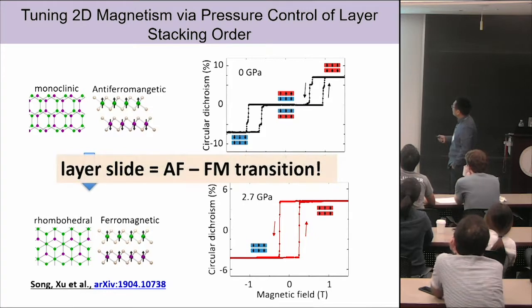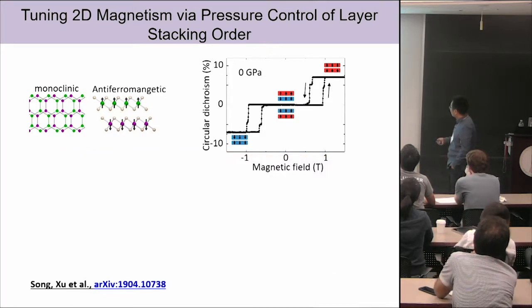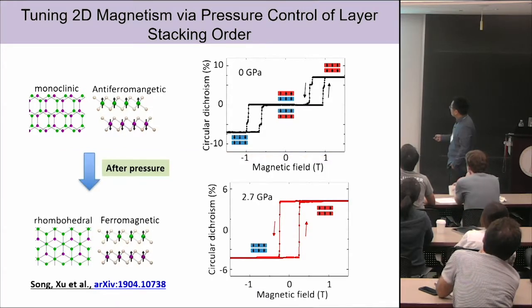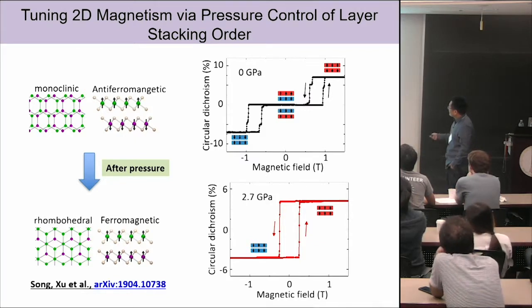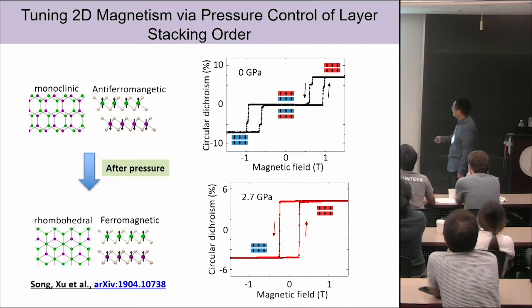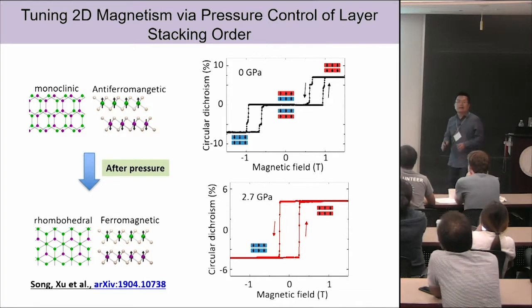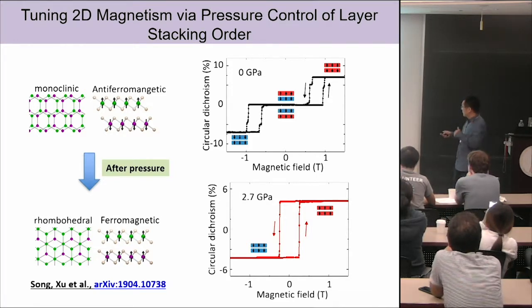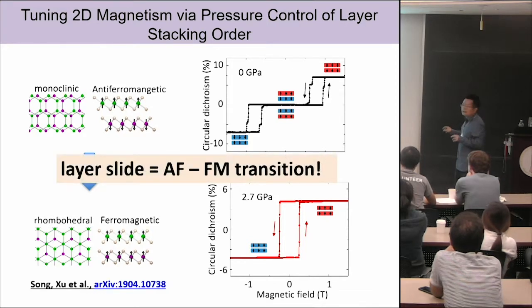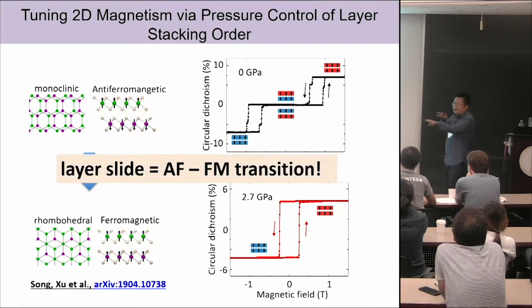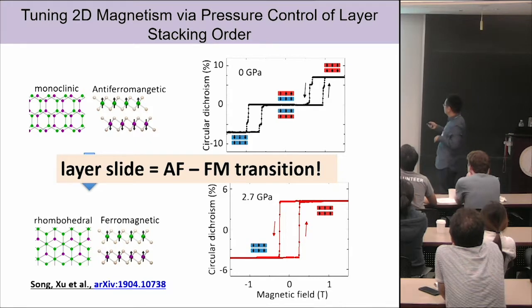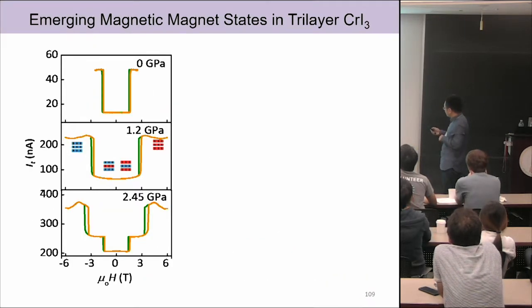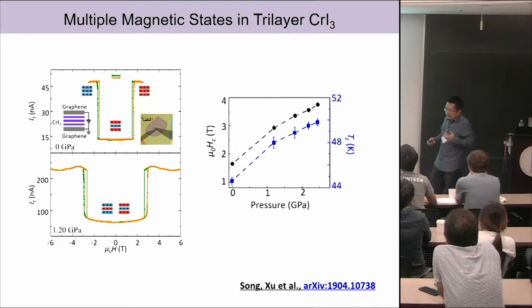Now for the sample after we apply pressure, the Kerr rotation signal is completely changed, right? Now we see a strong hysteresis curve. The bilayer now becomes a ferromagnet after the pressure. So the simple message is that this layer sliding actually tunes the system from antiferromagnetic to ferromagnetic. So what's interesting is, well, in the trilayer, we can actually engineer multiple magnetic states.